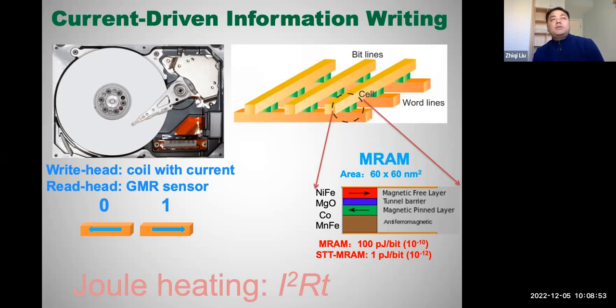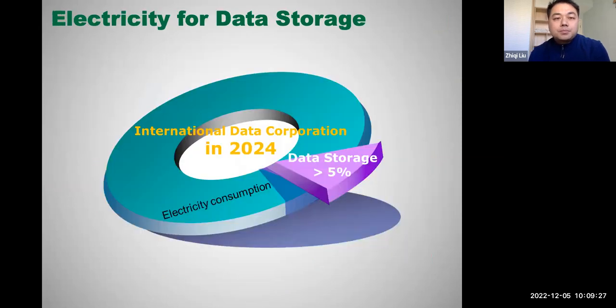As a result, the energy consumption for writing a bit for MRAM is still high. For example, for the conventional MRAM, you need a current to generate a magnetic field. The energy consumption is 100 picojoule per bit. For the spin transfer torque MRAM, the energy consumption is significantly reduced by around 100 times. You still need 1 picojoule for writing 1 bit. If we look at the electricity for data storage, as predicted by the International Data Corporation, in 2024, the electricity cost for data storage could be more than 5% of the electricity of the entire society. That's actually a significant number.